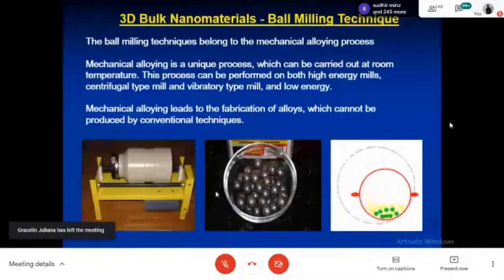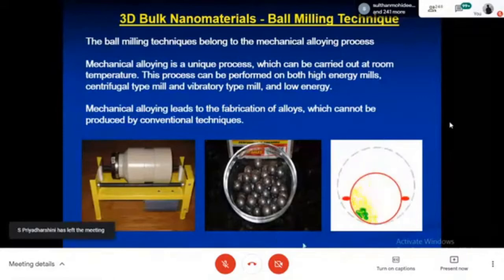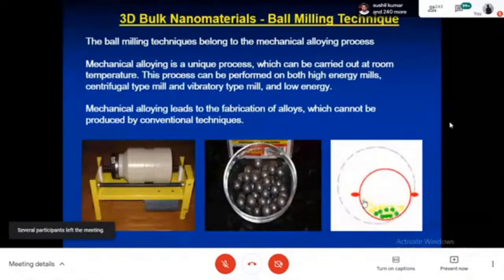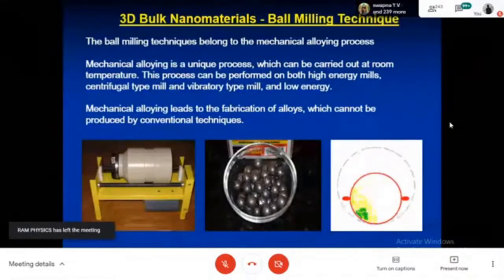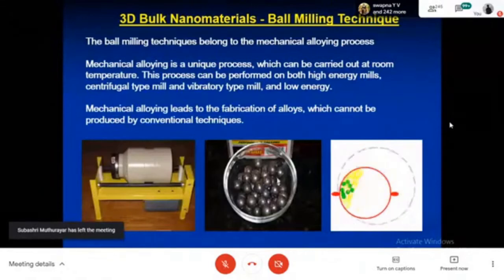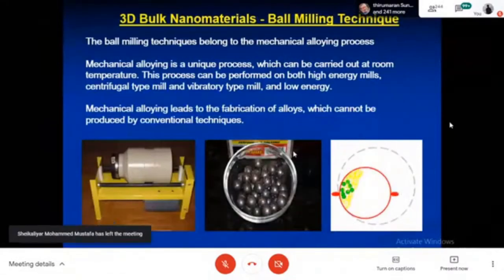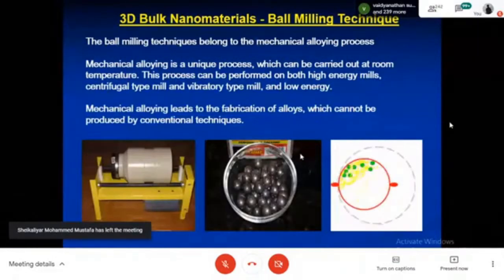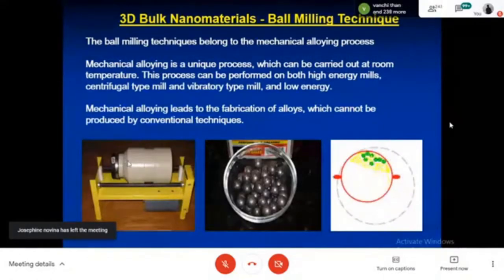This is where you take the material in solid form, whether it's micron size or a few millimeter size, and then introduce it with metallic balls. When this is subjected to cylinder grinding for a few hours, these materials undergo very severe plastic deformation, and this plastic deformation reduces the size of the particles. So this mechanism is used to make nanoparticles, and a particle size of around 50 nanometer can be conveniently synthesized by this ball milling process. And this is a typical small scale ball milling. It costs about 2.5 to 3 lakh rupees.